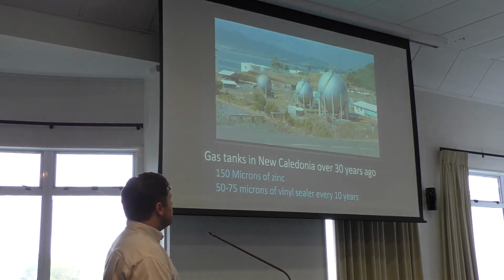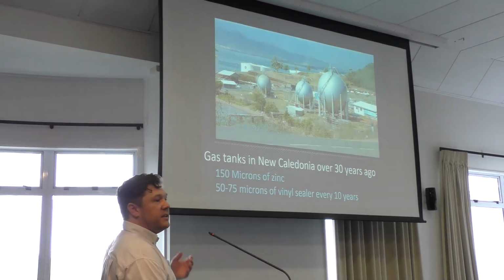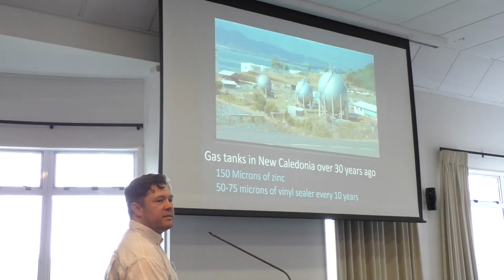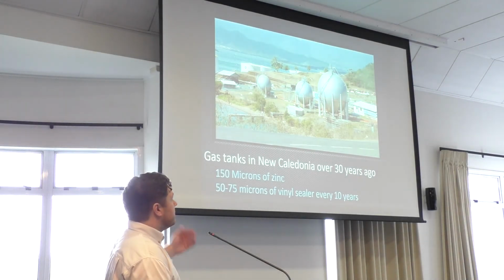Gas tanks in New Caledonia. Got 150 microns of zinc. I believe that was applied with flame spray, so it would have taken quite a bit of time to get that on there. 50 to 75 microns of vinyl sealer on that. They do the sealer every 10 years or so. So they do maintain this coating, but 30 years on and there's still no sign of corrosion on these products.